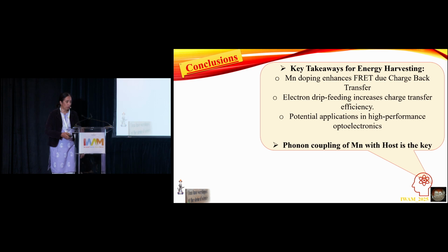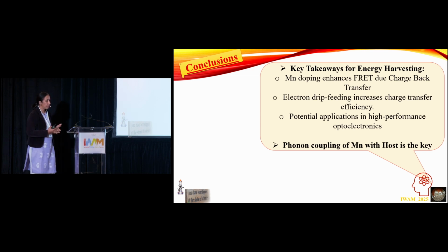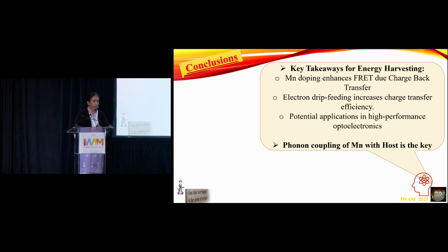Okay, so I think I've almost come to the last 10 minutes. I would like to summarize this talk by looking at the key takeaways for energy harvesting. Manganese doping enhances FRET due to charge back transfer, which is basically an electron drip feeding. This increases the charge transfer efficiency. Because of the drip feeding, although there is no Stokes shift, it gives me the opportunity to avoid self-absorption, and because of which it is also tunable. I'm just using the excitonic emission, it's still tunable, and it has potential applications in high performance optoelectronics.